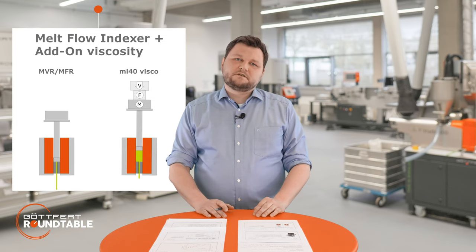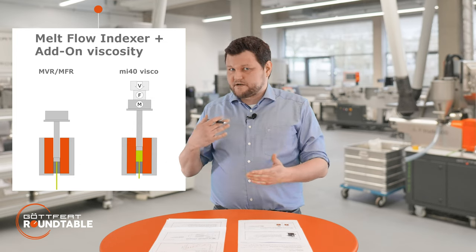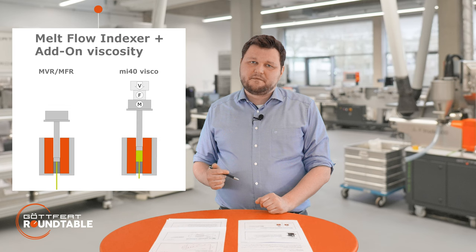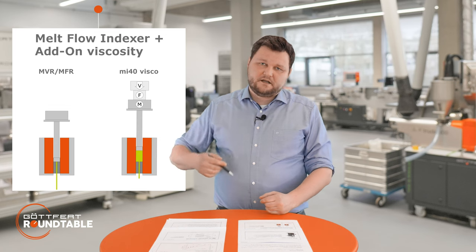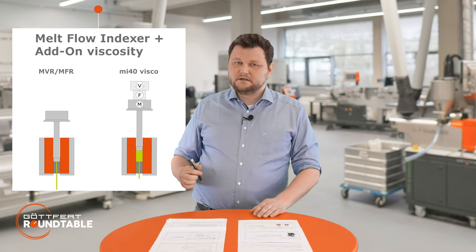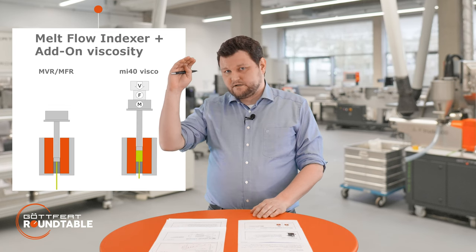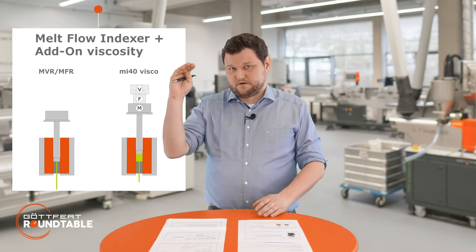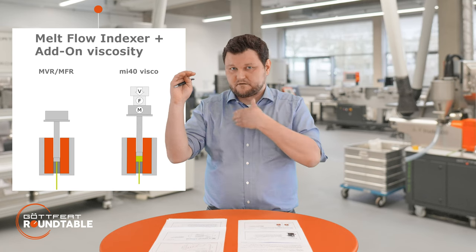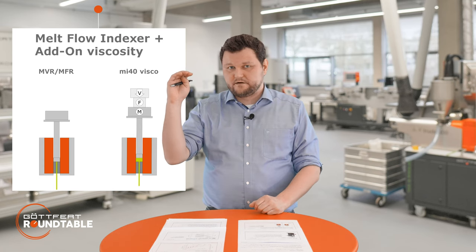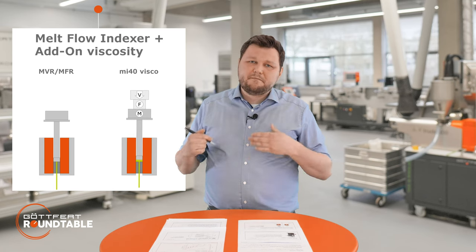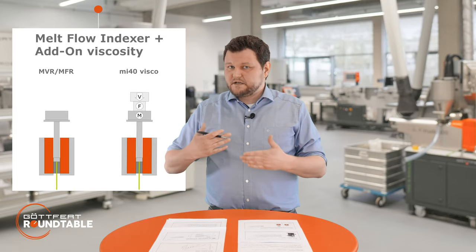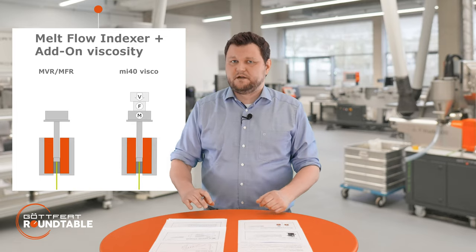With the visco option we will turn this measurement procedure around. We use the drive of the MI40 and a load cell, and we will drive the piston at set different shear rates — or piston speeds that correspond to shear rates — and we measure the force needed to reach that piston speed.